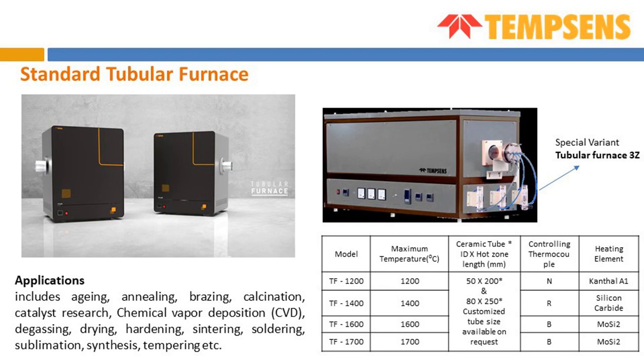And not only the standard tubular furnace with a single zone, we also provide multi-zone. Sometimes the customer needs a bigger hot zone, 500 mm or 800 mm. So a single control zone is not enough. So we can provide up to 3 zone, 4 zone, 5 zone, so that it can maintain a bigger length heating zone uniformly, so that your sample is uniformly heated throughout this region. And when the batch is larger, like 4 kg, 10 kg or 12 kg sample at a time, you can heat treat it in a good uniform heating zone. So a single controlling zone will not be applicable for this. We have to use multiple heating zones.